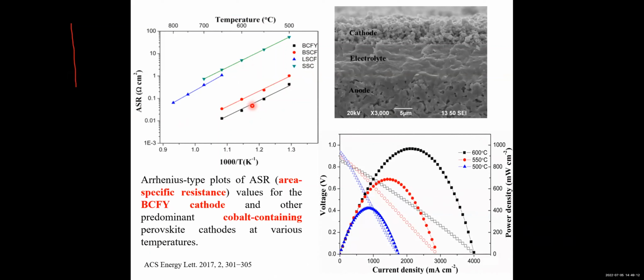Using this material, we fabricated SOFC, and we tested the SOFC performance at different temperatures. We achieved a very good power density, about 1,000 milliwatts per centimeter squared at 600 degrees Celsius. So this is one type of material we developed.